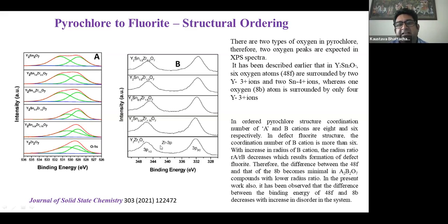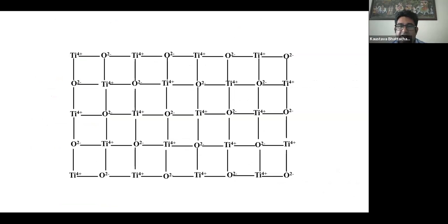Also, if we take the XPS of the zirconium, we find a strong shift, because its coordination number increases. As the coordination number increases, the oxygen around the zirconium increases. The oxygen, being more electronegative, pulls more electrons from the zirconium, so the binding energy around the zirconium also increases. So definitely we can show the order-disorder structure from the XPS parameters. Okay, I tried to explain one small doping study from XPS.